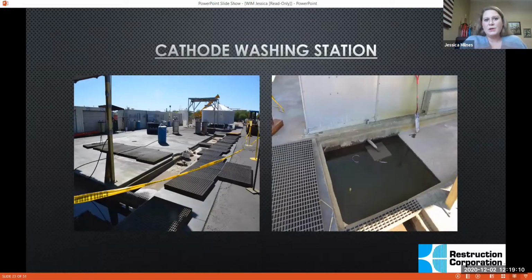Okay, so the third project I wanted to share with you, this one's down in Tucson. So it's not actually a mine, but when the cathodes at the mine are having an issue, they remove them and they either repair them or they replace them. So what they're actually doing at this facility is they're washing those cathodes. So the same acid is getting into their structure, which isn't necessarily on a mine site. So what happens is when they wash them over time, all of the coating has just worn away in this trench drain that is right here. So this is kind of the before.